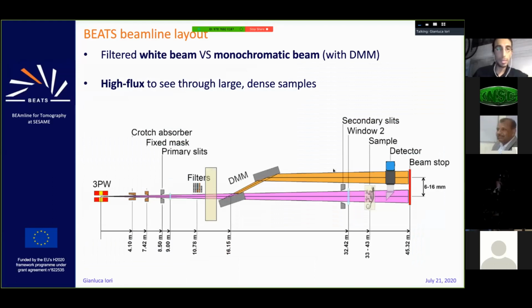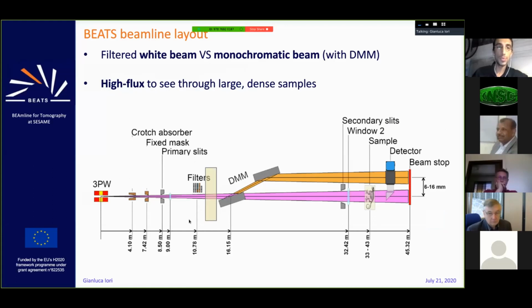This is also the layout of the beamline, but a schematic layout, and again, you see the total length. I'm looking at the picture now, 45-meter long beamline. On the left, there is the source. In the front end, there is equipment to absorb X-ray radiation that we don't want, we don't make use of. At 9 meters, we have the first window. It's a diamond window separating the ultra-high vacuum of the accelerator from the high vacuum of the beamline itself. And the last equipment that I'm showing here in the front end are filters. These are used to tune the energy, particularly to remove the low energies when we want to operate at high photon energies.